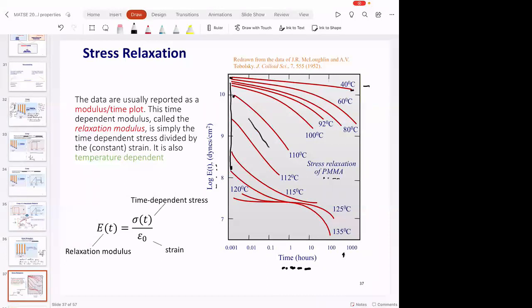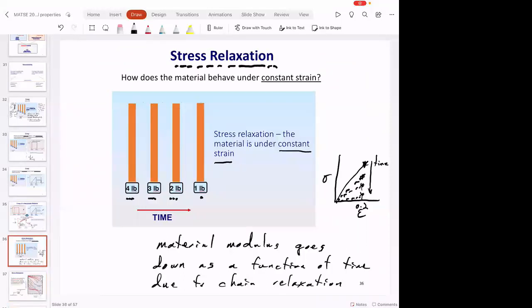But the slope of the line really starts to matter. The slope of the line is the rate of stress relaxation, and that happens much faster at higher temperature because the chains are relaxing faster. So you see a lot of cool plots like this, and eventually you get to pretty low modulus, which tells you that PMMA is not going to be very effective at this temperature because the modulus is really headed in the wrong direction if we want a stiff material. Whereas, let's think about these temperatures, and we can pick what's called an upper use temperature or an upper application temperature where the properties of PMMA are pretty good and we shouldn't go above this temperature or else it's just going to relax too fast or creep too fast. But you definitely want to look at this idea of the modulus changing as a function of time, and that's due to stress relaxation, just as we demonstrated here.